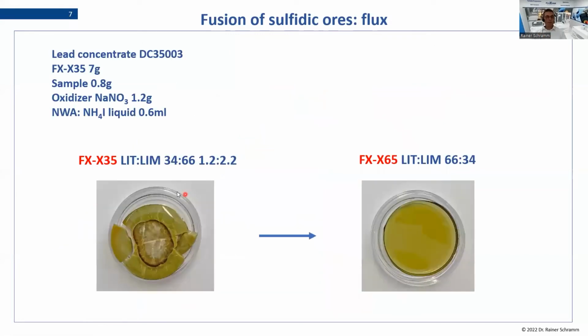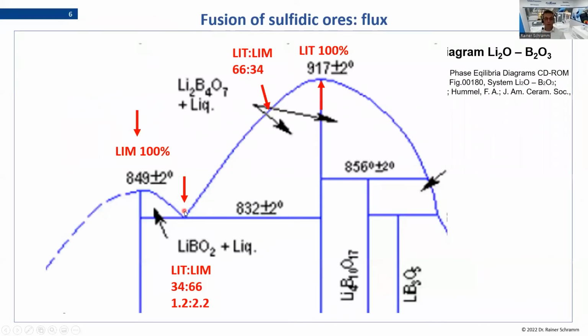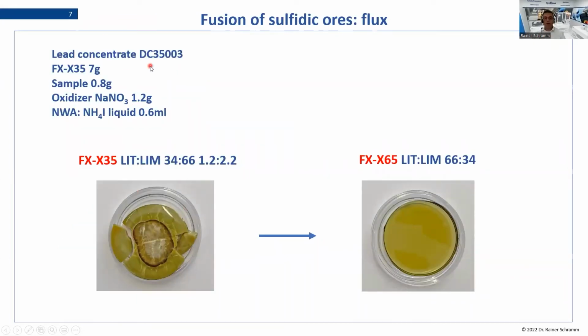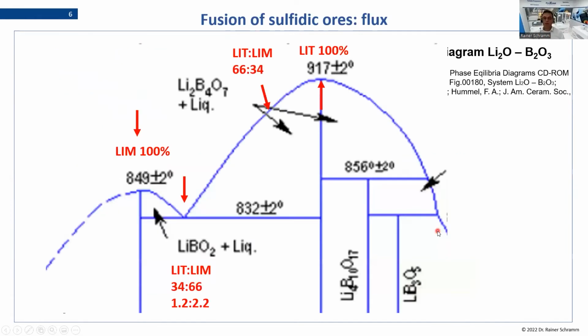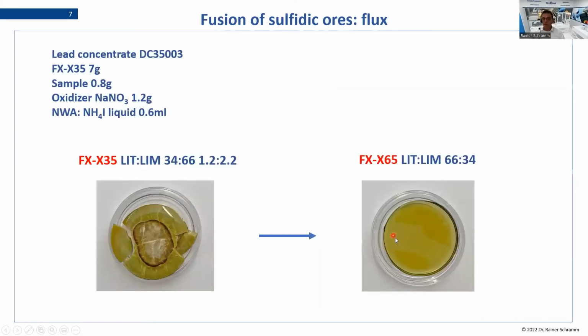I give you some examples. For example, here we have this flux 1.2, 2.2, so at this point, and we have here a recipe of a lead concentrate. So let's get back to sulfides, in a ratio of 0.8 gram sample to 7 gram flux, 1.2 gram sodium nitrate as oxidizer, and as non-wetting agent we use ammonium iodide. And in first trials, you see a bit of crystallization, cracking. But if we would do exactly the same recipe in a 66-34, so this kind of flux here, much better glass forming, we get a nice glass. So you see already the challenge between the two.